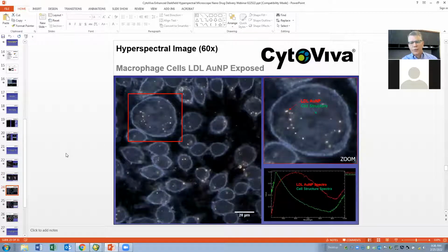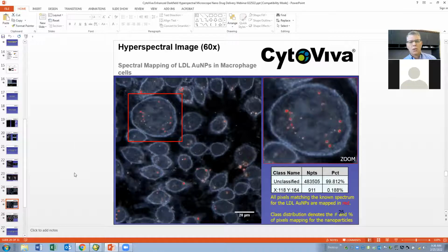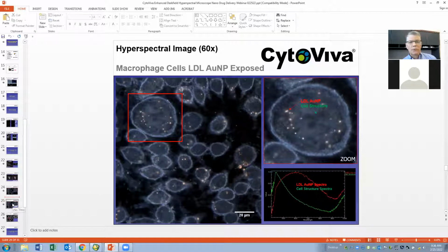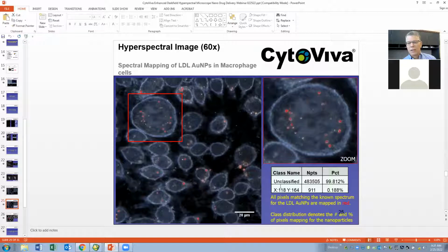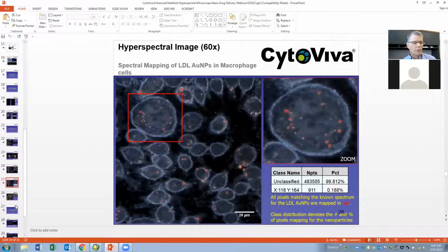I want to go back now, and this is the exact same sample that we were looking at a little bit earlier: the low-density lipoprotein gold nanoparticles in the macrophage groups. Here we're looking at the full image, and we can see LDL that's taken up by various macrophages. In this image, we're looking at spectral mapping of those, and we see really nice spectral mapping. Anywhere we see the LDLs present, we get a class distribution that gives us quantitative information relative to the mapping in the image, okay? And that gives you a sense of where those are.